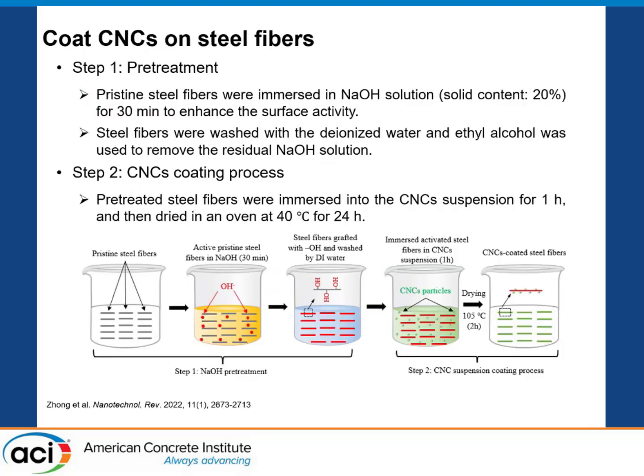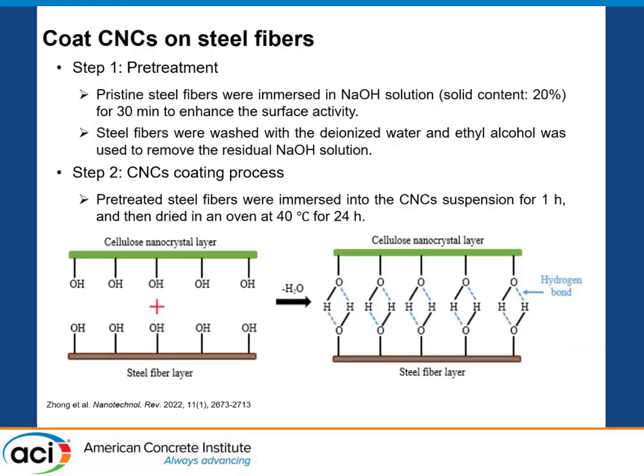So here are our methods to coat the CNCs. First, we do a pretreatment for the pristine steel fibers. The pristine steel fibers were immersed in sodium hydroxide solution for 30 minutes, and then we removed the residual sodium hydroxide solution. After that, step 2 is a coating process. We immerse the pretreated steel fibers into the CNC suspensions with different concentrations for 1 hour, and then we dried them in the oven at 40 degrees C for 24 hours. With that, we can have the CNCs coated on the surface of the steel fibers, generally through hydrogen bonds.